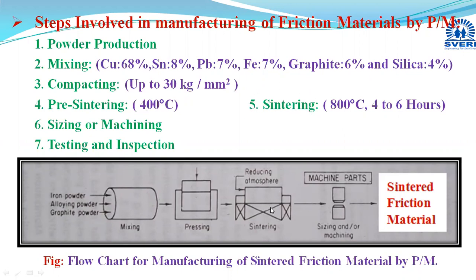Now, in this sintering operation, the compact, which is pre-sintered now, is heated at 800 degrees Celsius, a high temperature region, for 4 to 6 hours. Here the sintering time is very high. Now at this temperature, what will happen? The tin particles will melt and start diffusing onto the copper and other iron particles. Due to this, a decrease in the shape and size of that component will occur, which is termed densification.